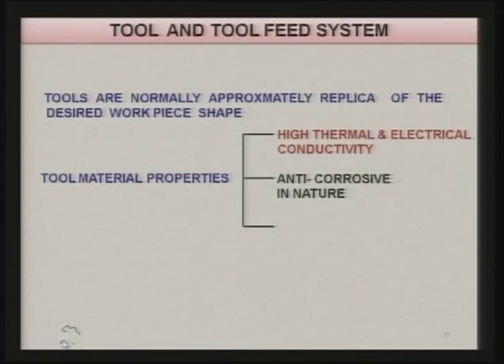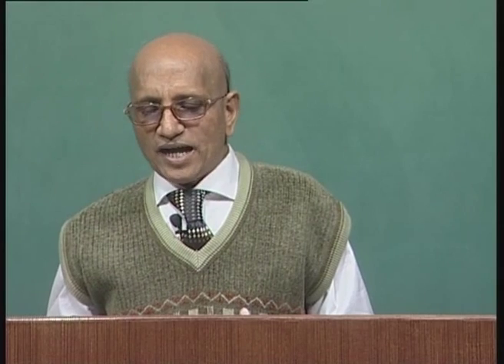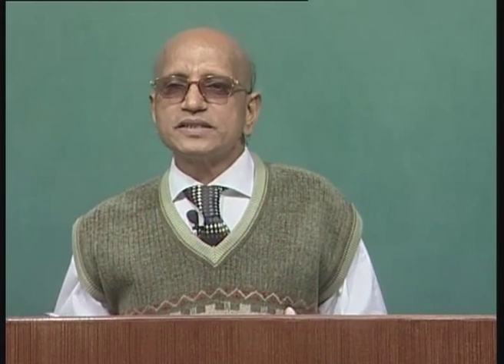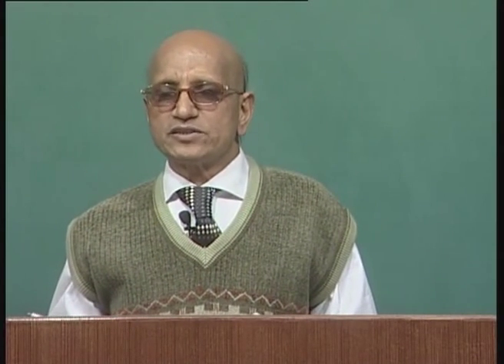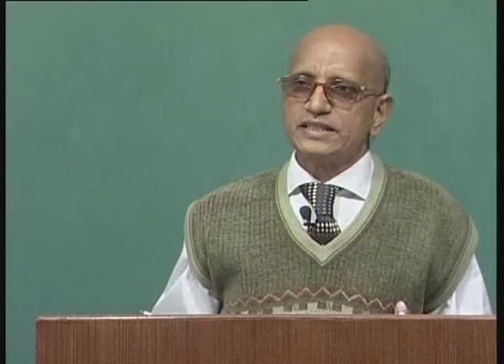If electrical conductivity is low, you will get higher heat generation, which raises temperature and changes the predicted tool and work piece profile. Another important property is anti-corrosive nature of the tool material, because tools and work pieces are both immersed inside the electrolyte, and most electrolytes are corrosive. If the tool material is not anti-corrosive, the tool itself will get corroded, its shape and size will change, and you will not get the desired work piece profile and dimensions.